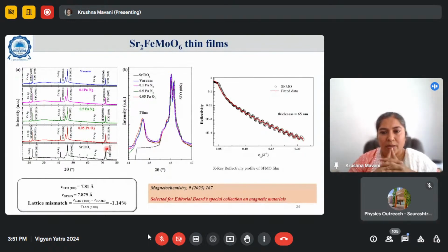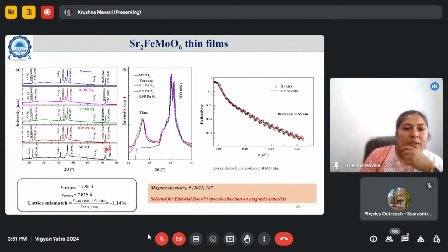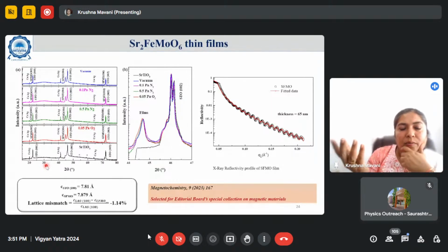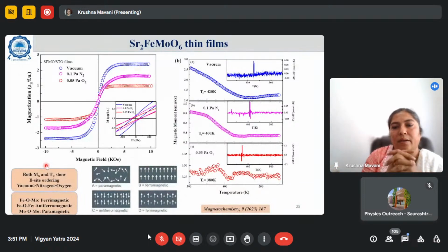That was published in Magnetochemistry recently, and it was selected for a special collection. We could see that as we change the gas pressure, the highest cation order was observed only in vacuum. So later on, whatever we deposited, we went ahead with vacuum only. These films, again with different gas pressures, always achieved the maximum in vacuum, shown here by the highest magnetization. Now you may ask me why highest magnetization shows that it is a high cation order.